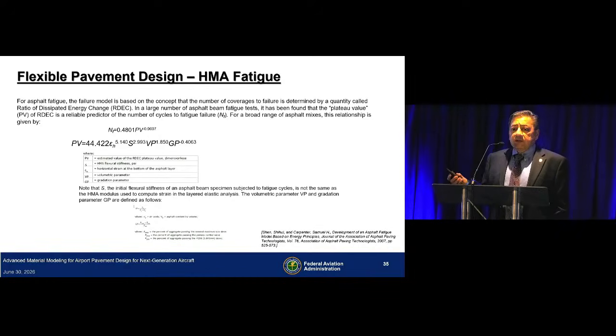Now, we did do some tests in construction cycle 7 to validate and refine the model, and what we found was that the number of cycles it takes to cause alligator cracking, because in the field, fatigue is defined by the occurrence of alligator cracking, is about 3 times the number of cycles predicted by this model. Which makes sense because the failure in the model is reduction in stiffness to 50%, which is microcracks, whereas with alligator cracking, you're looking at almost full depth cracks in the asphalt layer.